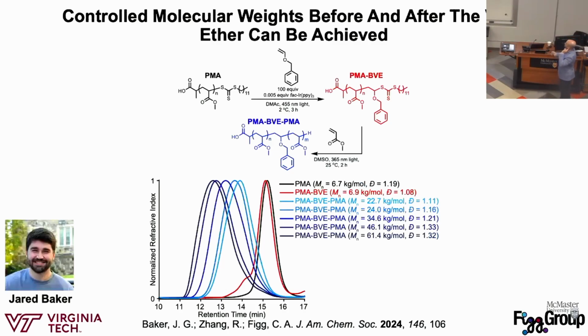In this paper, we were trying to put exactly one vinyl ether, or one monomer, at a defined position within an acrylic polymer. This is challenging because radical polymerization usually follows a Poisson growth distribution, so it's a statistical likelihood of adding monomers. You can't say, I want one monomer at this place and only one monomer at this place, and then chain extend it. That's really challenging to do in polymerization. We were able to do that by playing with kinetics and temperature to make sure that we were only getting one addition of this monomer at a defined position. We're really excited about it.